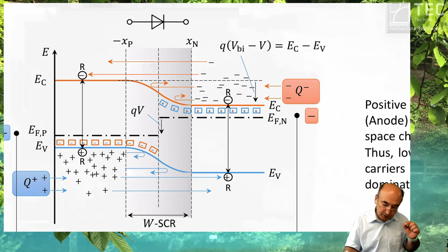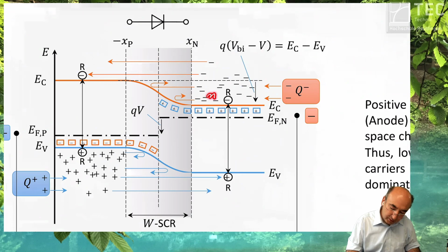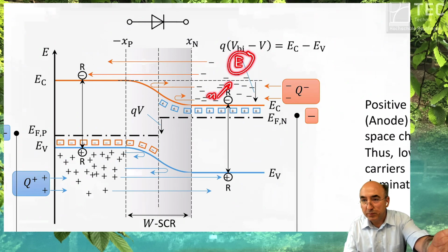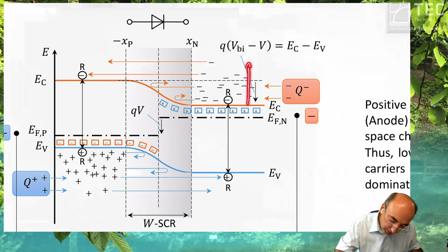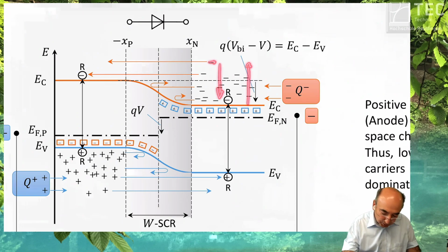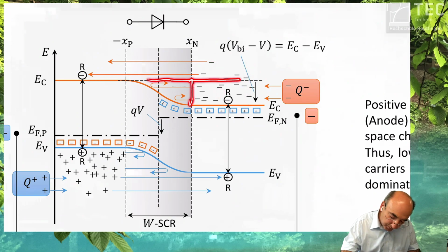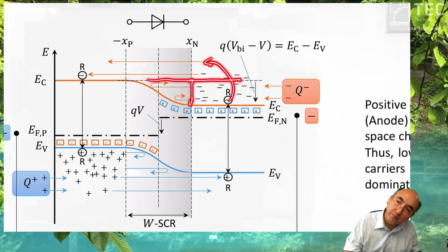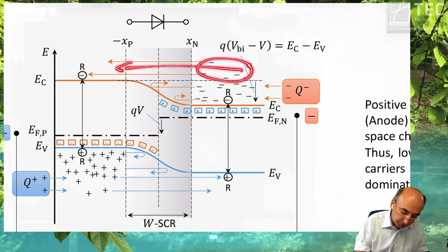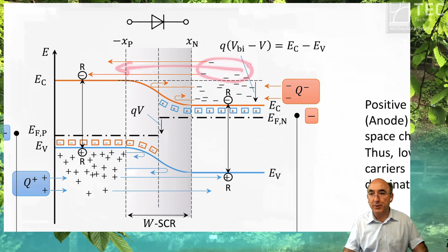The Boltzmann approximation says the concentration increases exponentially as a function of the energy, or reduces. By increasing the energy, the concentration is reduced, or vice versa, reducing the energy, the concentration is increased. So in reducing the barrier you have to overcome, the amount available for diffusion increases exponentially.